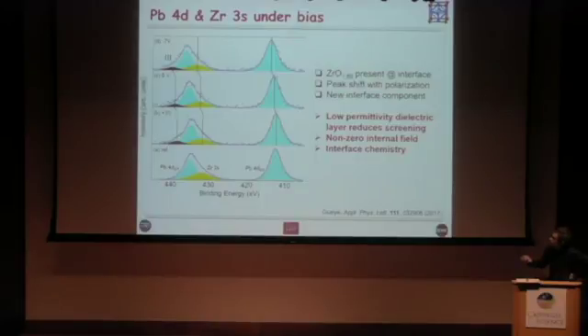Secondly, there is this additional peak. It's a singlet. Therefore, it must be related to the zirconium 3s. It can't be related to the lead. And this exists also for all biases. So what we know is that these nanostructures are present at the interface, that as the bias changes, there is a polarization-induced shift in the electronic levels at the interface, and there is some specific interface chemistry.